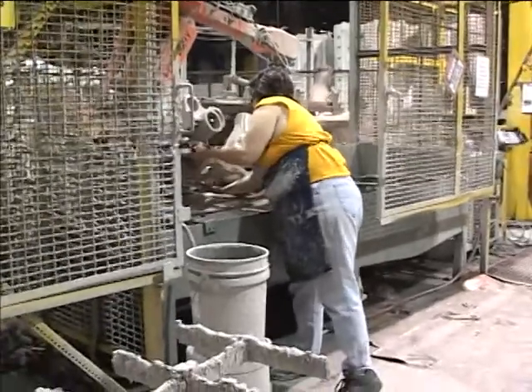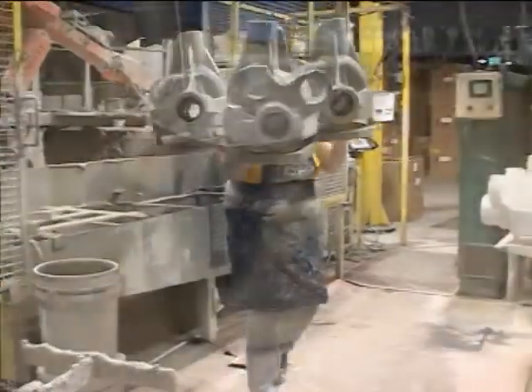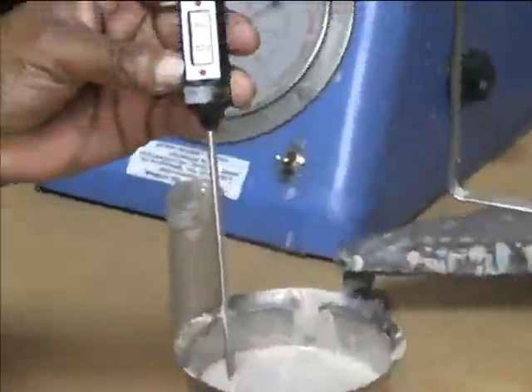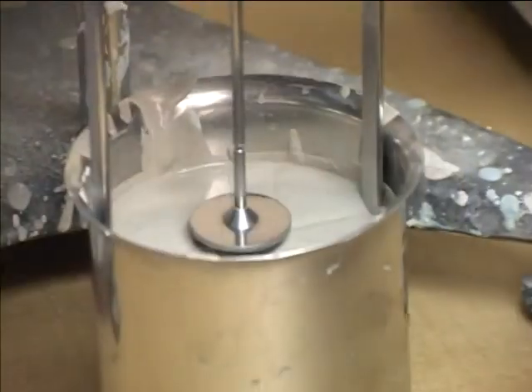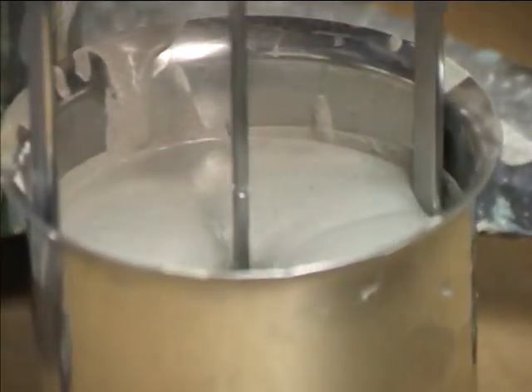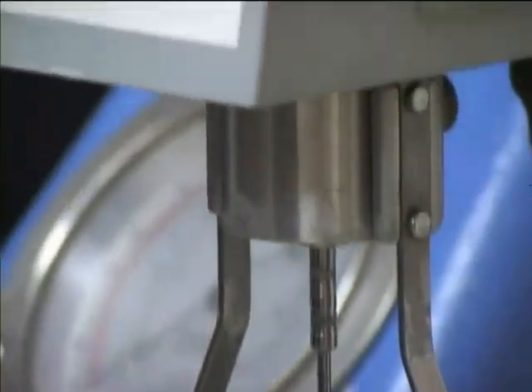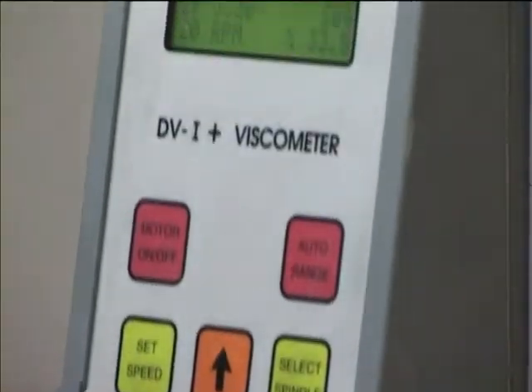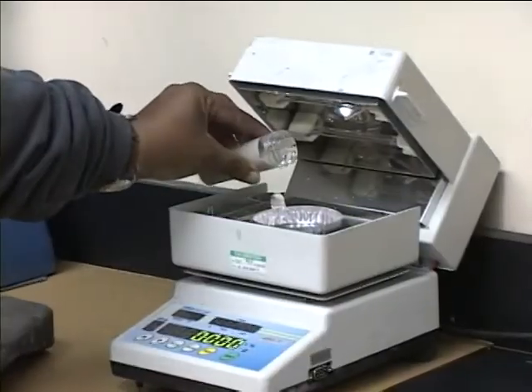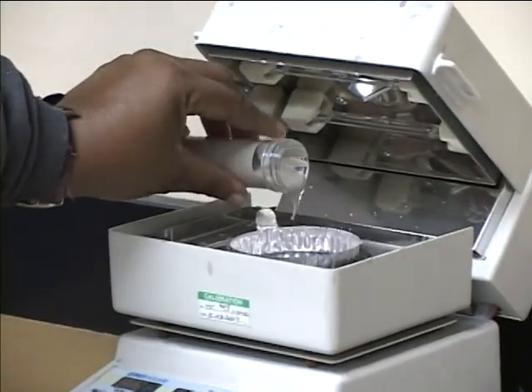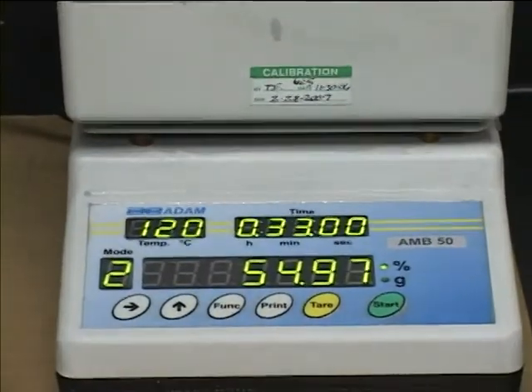The coating is a key factor in the entire process and is very carefully controlled through testing for viscosity and permeability because it has to control the velocity of the foam's gas dissipation. Too fast, and you end up with carbon impurities in the casting. Too slow, and the mold collapses in on itself due to the outside pressure of the unbonded sand.